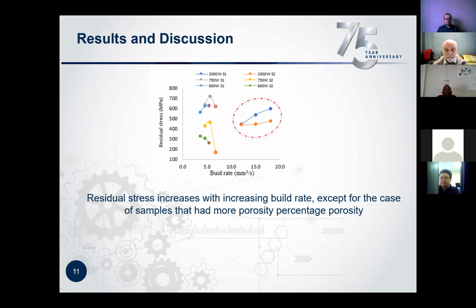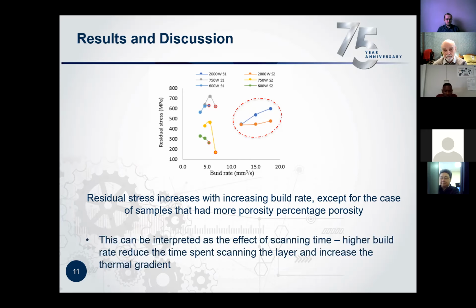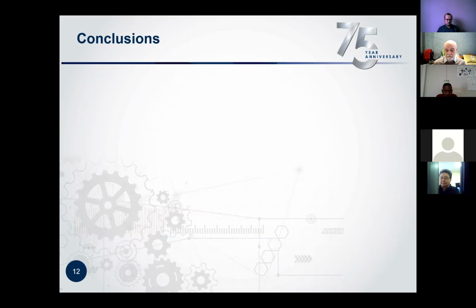However, when we look at the high power samples, which were produced at 2000 watts, where we varied the hatch spacing, we can see an increasing trend between the residual stresses and the build rate. As you increase your build rate, the residual stresses develop. And this can be interpreted as the effect of the scanning time. So you can imagine if you're increasing your build rate, most likely by increasing your scanning speed or increasing your layer thickness, this is going to give you high thermal gradients because now the interaction time is less. So you're going to end up having high thermal gradients in your molten pool, between the molten pool and the underlying material, and this can lead to the development of high residual stresses in your part.